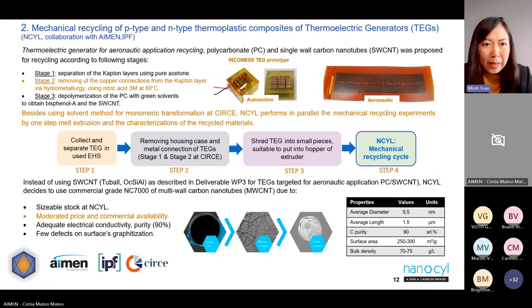In the second part, I talked about the mechanical recycling of the P-type and N-type. As you see in work package 3 presented by Maria this morning, we have the polymers for applications in automotive and aeronautics, based on polycarbonate and PEEK. We are assuming that all of the TEGs are used and collected, and we have already removed the housing case of epoxy and metal connections of copper, etc. Then we use the composites of thermoplastic polymer and carbon nanotube, shred them into small pieces, and they are ready to put into the hopper of the extruder.